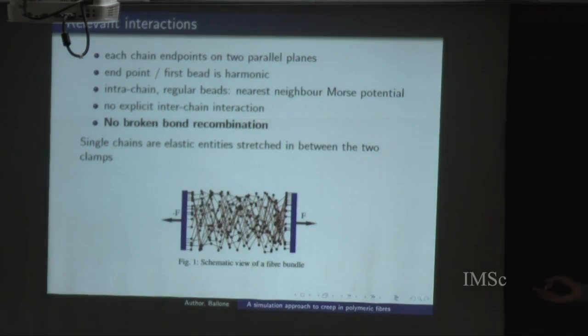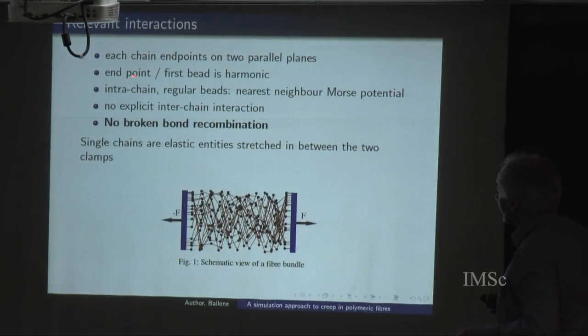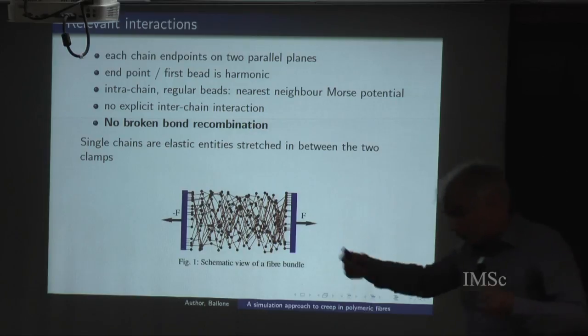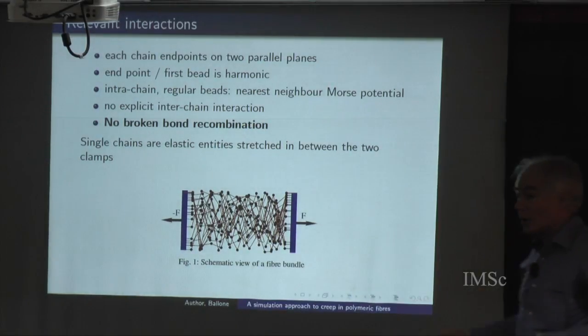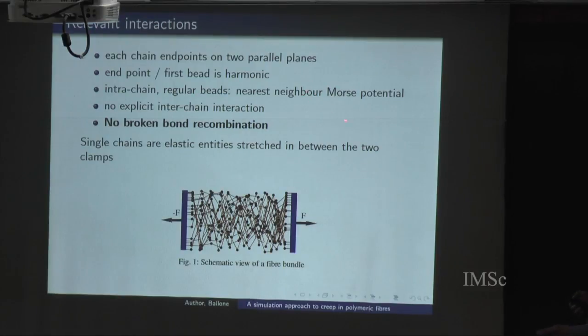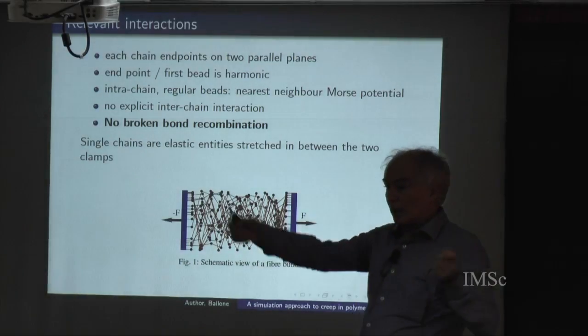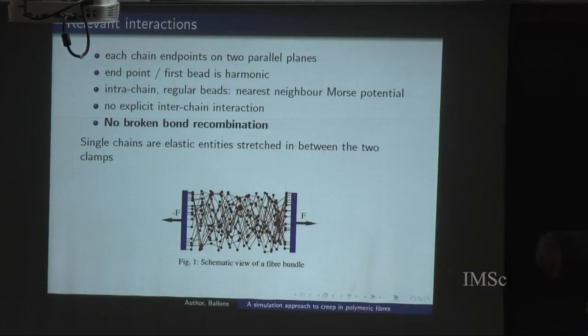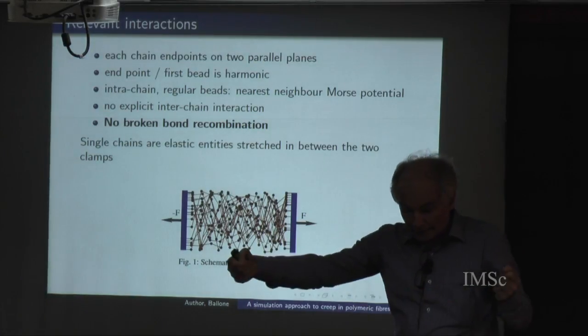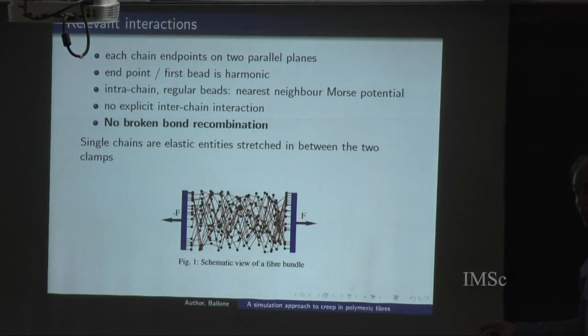So it's something that you will never break. But along the chain, the chain is defined by a sequence of what we call covalent bonds that are strong bonds, but strong bonds that can be broken. The potential is a Morse potential that has a finite well depth. So when we exceed the binding energy of the bond, the bond can be broken. It can occur because we apply a tension. It can occur simply by thermal fluctuation. So eventually, if you wait long enough, every bond will break.